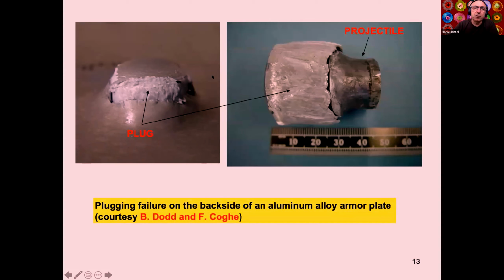Okay. If you shoot a blunt projectile onto a plate, what you will see is a plug being ejected. Well, the boundaries of that plug are, in fact, an adiabatic shear band. But the same would occur if you machine a metal. When you cut a metal by machining, you in fact delineate a couple of shear bands, and this is what you are cutting on. This is how you're cutting the metal. And if you want to look at the overall picture, that's the way it looks: your blunt projectile and the plug that is ejected with those boundaries of the adiabatic shear band.